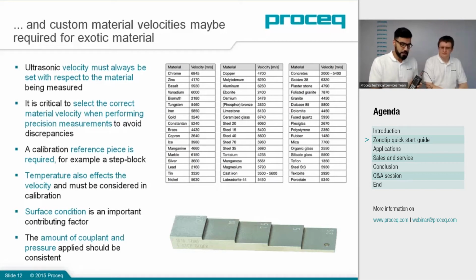One of the things that is fairly common, and we were talking about this a few days ago, is the amount of coupling paste that you apply on your reference sample and your real sample in the test, and also the pressure that you apply. That makes a difference. We discovered you can get up to 3 dB difference in the amplitude received, which is significant and will affect your thickness measurement to a large degree. So it's always good to consider these little side notes.